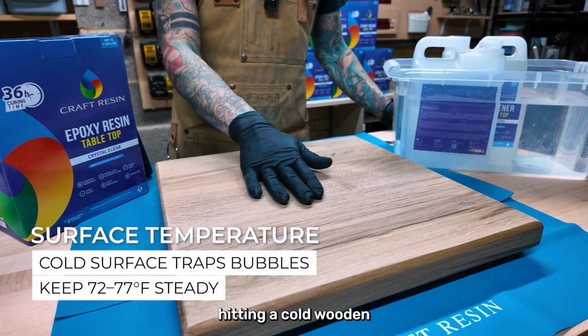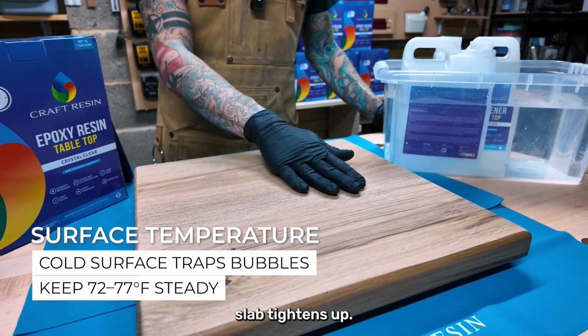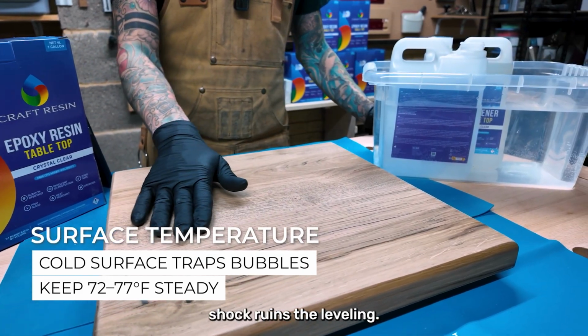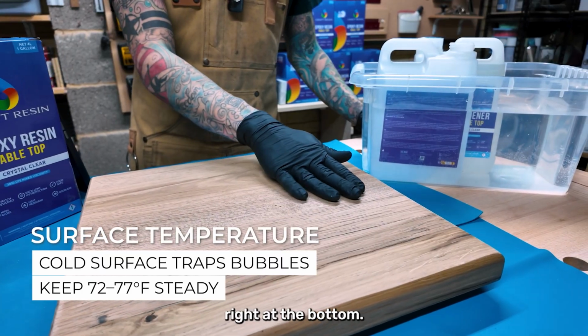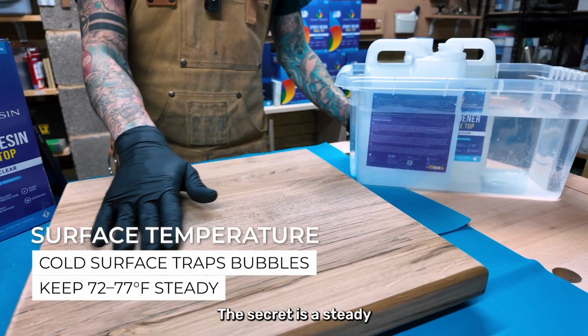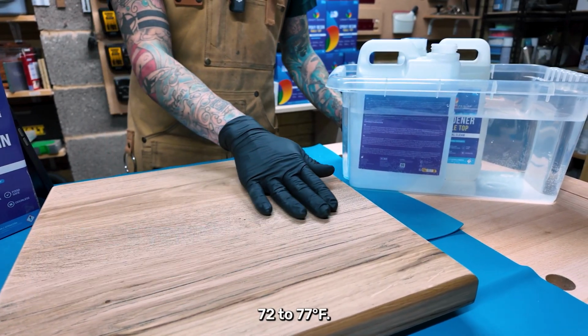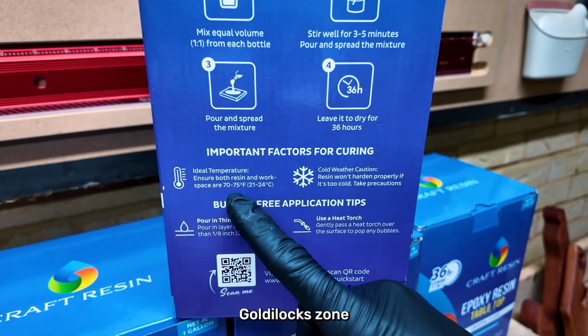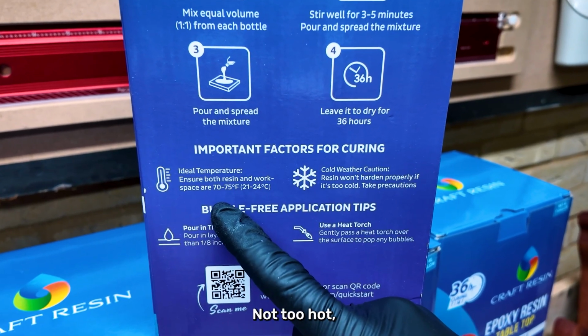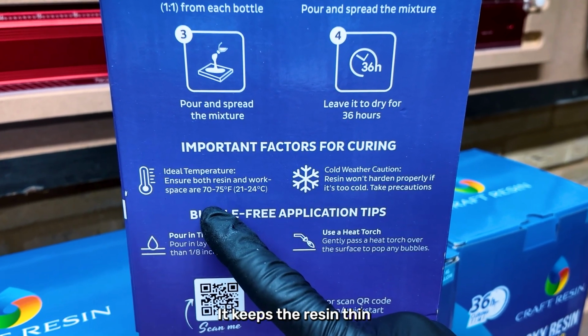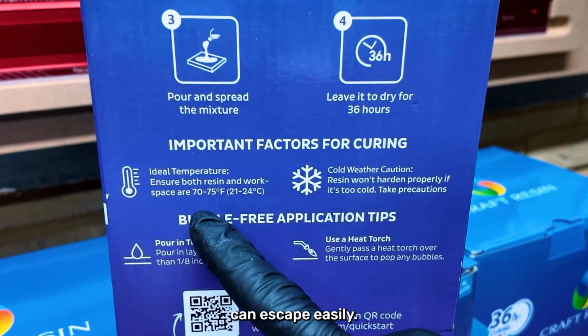A cold surface is also a problem. Warm resin hitting a cold wooden slab tightens up. This thermal shock ruins the levelling. It locks bubbles right at the bottom. The secret is a steady 72 to 77 degrees Fahrenheit. This range is the Goldilocks zone for craft resin. Not too hot, not too cold. It keeps the resin thin so bubbles can escape easily.